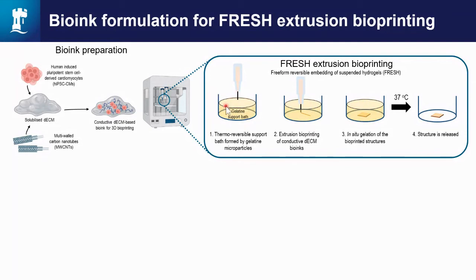This is because the viscosity of our inks is quite low. So the gelatin bath allows us to retain the shape of our structures and avoid the structures collapsing. So what we do is we print inside the gel. And once the structure is fully built, we wait for the in situ gelation. We use the gelation of the structures in situ, inside the gelatin bath. And then we increase the temperature to 37 degrees to melt the gelatin microparticles and then release our structures.